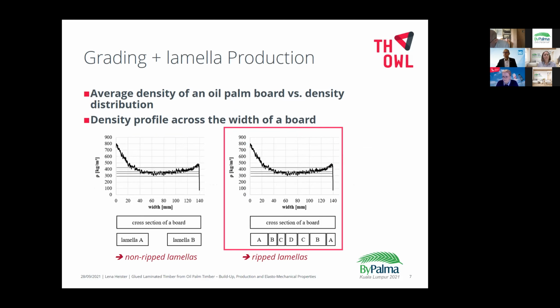In this picture, you can see on the left side the density profile along the width of an oil palm board from the outer zone, measured with X-ray. The density of the board varies across the width from nearly 800 kilograms per cubic meter on the left to approximately a density of 350 in the middle and up to 450 kilograms per cubic meter on the right side. When cutting full-size lamellas for the production of GLT as conventional, there will be lamellas with an inhomogeneous density distribution along the cross-section. The cutting of the lamellas is done alternating from the edges due to the tapering of the